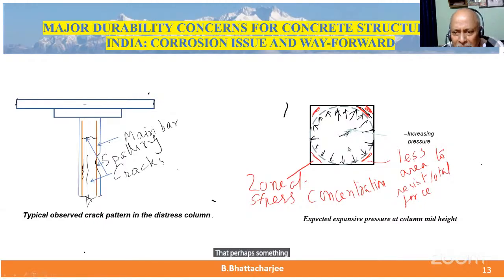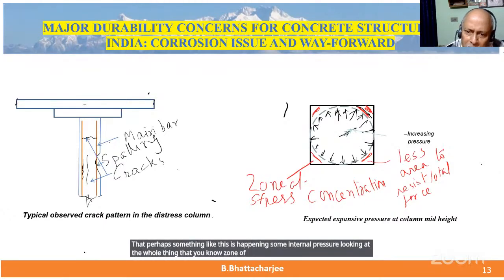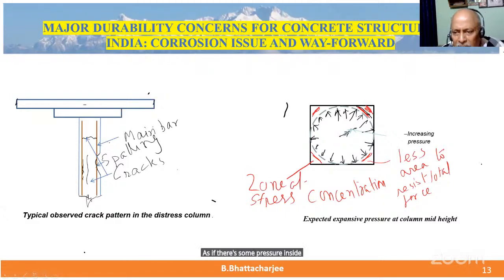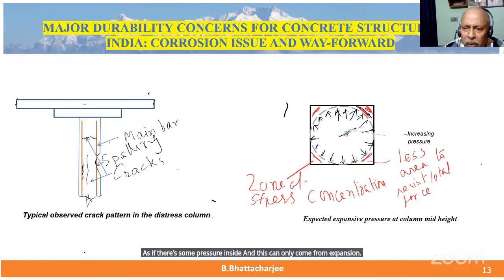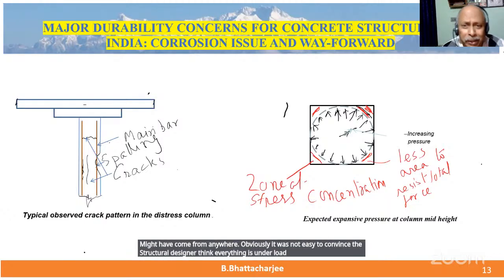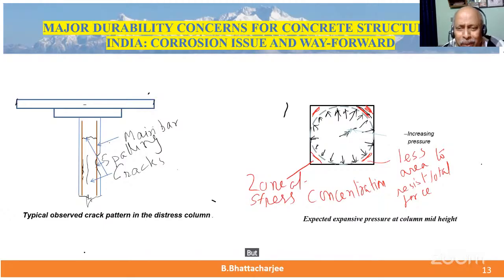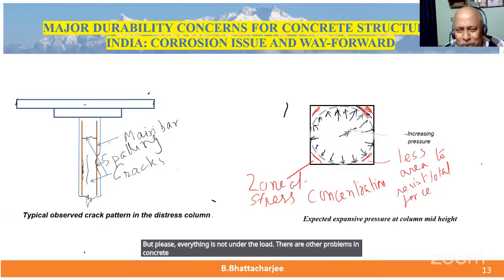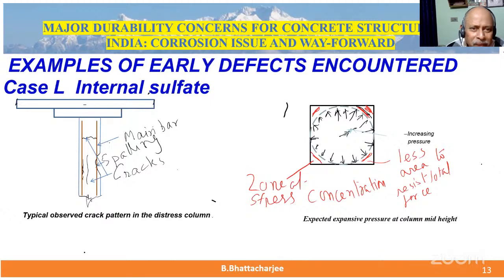So what I guessed was that perhaps something like this is happening, some internal pressure, looking at the whole thing, the zone of stresses, the concrete spalled off here, as if there's some pressure inside. And this can only come from expansion. And my suspect was that there is some sort of sulfate in the system. Might have come from anywhere. Obviously, it was not easy to convince the structural designer, who thinks everything is under load and nothing else. Sorry, you are all structural engineers, but please, everything is not under the load. There are other problems in concrete too. Most of these cracks I am showing have hardly anything to do with the load. So internal sulfate, that's what it was.